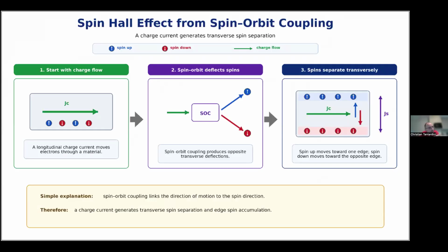responsible for spin-orbit coupling. So about the spin Hall effect, one of the concepts that I would like to introduce, the spin Hall effect comes from the spin-orbit coupling. So when we have a current like this, and we have a strong spin-orbit coupling, we will see that we will have a spin current that goes one from the up and the other from the down spin. And so we will see that the electrons will be aligned in two different places, making spin up and spin down. So this is a simple explanation of where spin-orbit coupling makes a difference. If we have no heavy element, spin-orbit coupling will not be present. It is not true that it's not present, but it is so low that it cannot deflect the spin at the